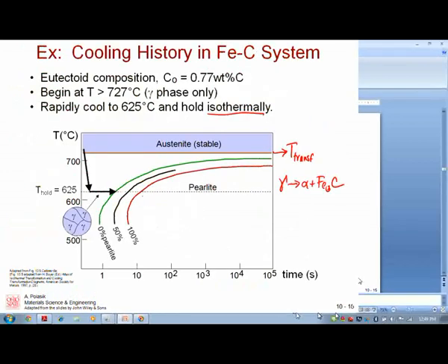Okay. So let me go back here. We talked about pearlite. This is the one we've been talking about. Why? Because it's the equilibrium eutectoid microconstituent. Equilibrium means it's what's going to form if we cool it slowly enough and maintain equilibrium as we go through. Eutectoid means it's that lamellar back and forth, and it's happening because of this eutectoid transformation. And a microconstituent is this combination of the two phases, alpha and Fe3C, and their orientation with respect to each other in the microstructure in 3 dimensions.